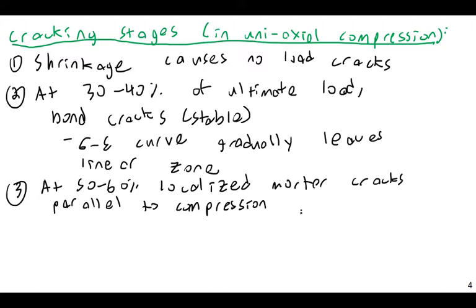At stage three — 50 to 60% of ultimate load — you get localized mortar cracking. This is where the mortar starts to crack across the paste boundaries, parallel to the compressive forces. This is sometimes referred to as the discontinuity limit.